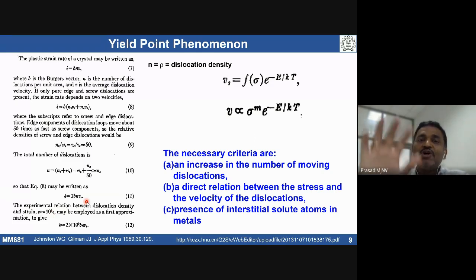So the increased dislocation density can bring down the velocity of dislocation, if you talk about no solutes being there. So the dislocation velocity can come down, only in order to maintain stability in the deformation, to deform the material at the same rate of what you are applying.